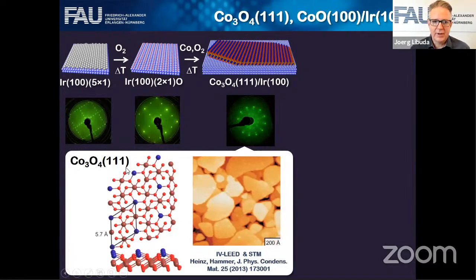This is an example of a cobalt oxide 111 film. This system has been developed and characterized in the group of Klaus Heinz and Lutz Hammer, and now by Alexander Schneider at our university in the Department of Physics. And this model system is beautiful because it is not only well ordered, but you really know where the atoms are. So there's not only STM, which is very important, but for instance, there are LEED IV structural analyses that tell you exactly where the surface atoms are.